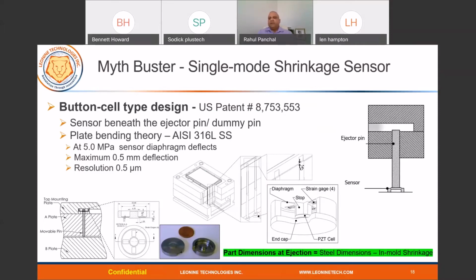So here is the mechanism: the sensor is placed beneath the ejector pin or the dummy pin. When the plastic melt enters, that plastic melt will exert force on the pin, which will deflect the diaphragm of the sensor, which is designed to deflect at 5 megapascal, almost the time the melt comes in contact with the pin. And once the part shrinks, the melt will shrink away from the metal steel or the cavity wall. The pressure will decay. When the pressure reduces below 5 megapascal, the pin will push upward. And during this motion, it will measure the in-mold shrinkage.